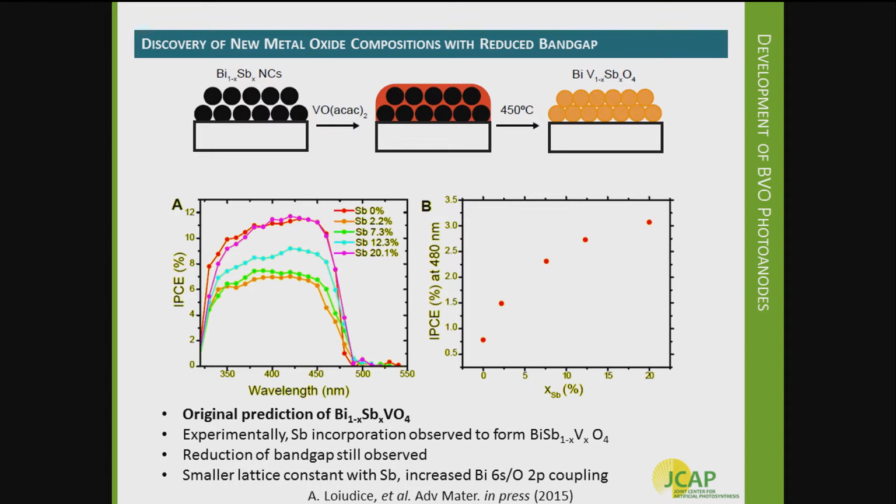However, she was able to show that the band gap was reduced by a few hundred millivolts, from this 2.5 value to about 2.3, which is great in terms of going in the right direction towards having a material that can capture a larger fraction of the solar spectrum. And these reductions of the band gap corresponded ultimately to increases of the photoconversion efficiency.